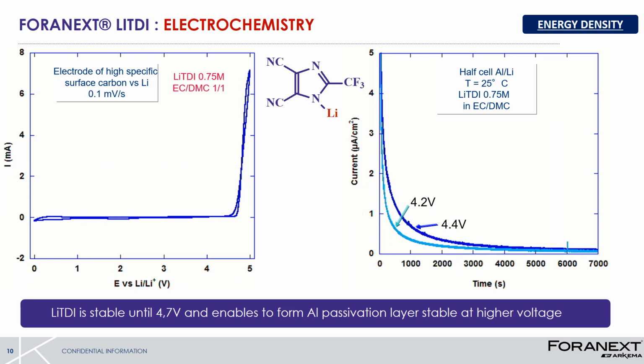From an electrochemical point of view, the LiTDI is really stable. Indeed, the electrochemical degradation of LiTDI occurs beyond 4.7 volts. Moreover, LiTDI, as shown on the chronoamperometry, is able to form quickly a stable aluminum passivation even at higher voltage.